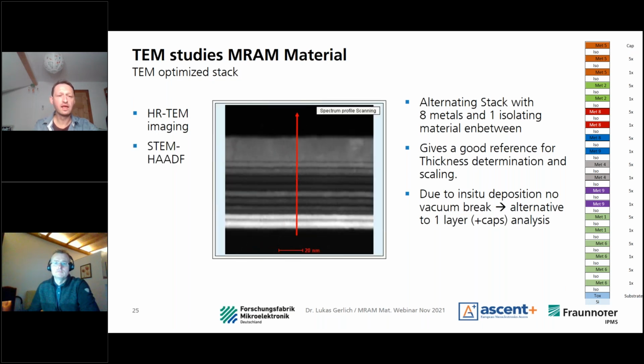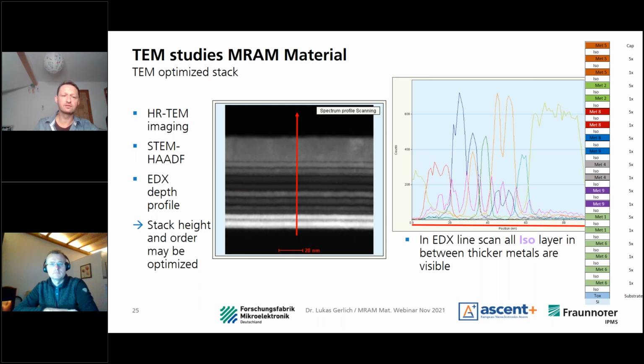So for STEM HAADF, you can also see a different contrast. Also, the isolation material can be seen, and in the EDX depth profile you can see, for example, the isolating material alternating in between the metals.